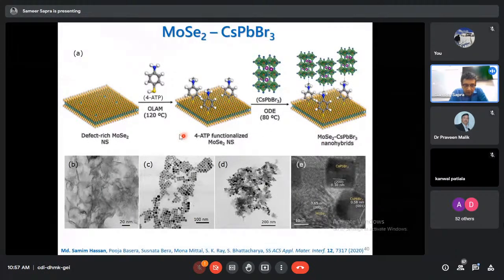defect-rich molybdenum selenide, and I know that all the thiols go and bind over there. So let me take a thiol, which is 4-aminothiophenol. Okay, so thiol on one end, amine group on the other end, and put it like this, nicely decorated, and throw in some cesium lead bromide. The ammonium cation goes and attaches to the bromide anion. These are all ionically attached, so all ionic bonds over there, and forms very nice heterostructures.